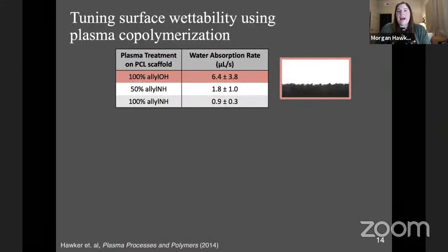So after treating the scaffolds with the different plasma precursors, I used contact angle goniometry to measure how water interacted with the scaffold. So remember that the water drop sat on top of the scaffold before it was exposed to the plasma. After plasma treatment, I'm showing in the video an allyl alcohol modified scaffold. I observed that the water drop was absorbed by the scaffold, and this is shown by the looped video. So this demonstrates that we've effectively enhanced the surface hydrophilicity of this scaffold through plasma treatment. And importantly, we didn't see any changes in the three-dimensional network of the scaffold. So we retained that, but selectively changed its surface properties.